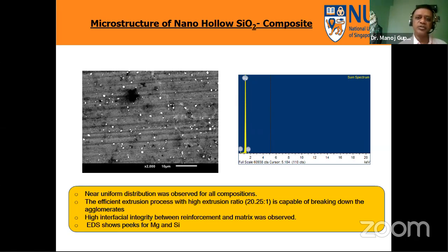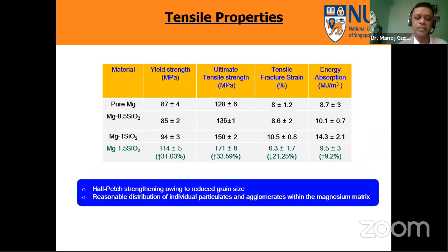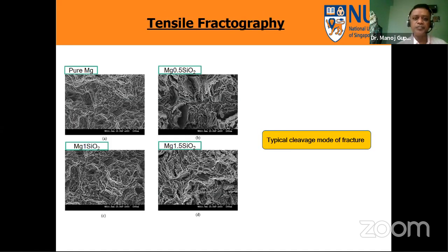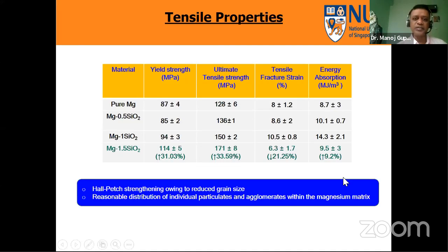This slide shows a similar result for nano SiO2 particles. SiO2 is also very biocompatible—at times it's also called bioglass. Then we look at the tensile properties, and see how they change with the amount of reinforcement. The best properties are exhibited by 1.5% SiO2, and even 1% SiO2 gives wonderful ductility, acceptable UTS, and very good energy absorption under loading.